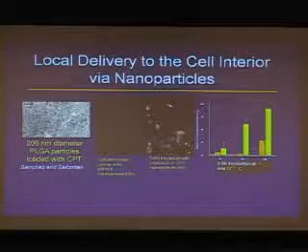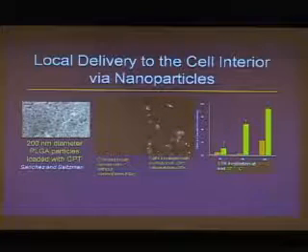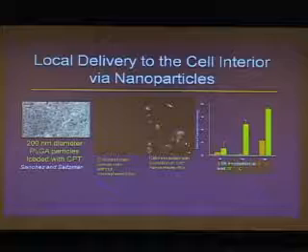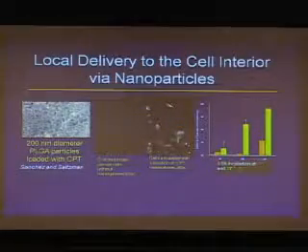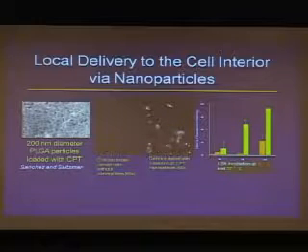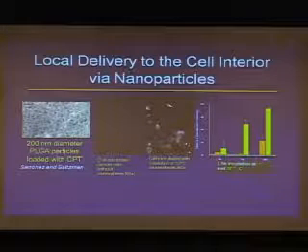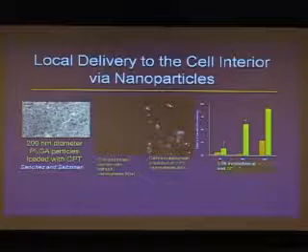One interesting feature of being this size is that these particles, being less than 200 nanometers in diameter, are much smaller than tumor cells. So these are breast cancer cells in culture. These particles also have the property that they're fluorescent, because the camptothecin that's within them is fluorescent. So if you incubate these particles with cancer cells, what you'll find for many different kinds of cancer cells is that the particles relatively rapidly enter the cells, and they fill up the cytoplasm of cells like shown here. You can see that the cytoplasm in these cells is fluorescent because they've taken up large quantities of these particles when they were just added to the culture medium. So nothing special done there.